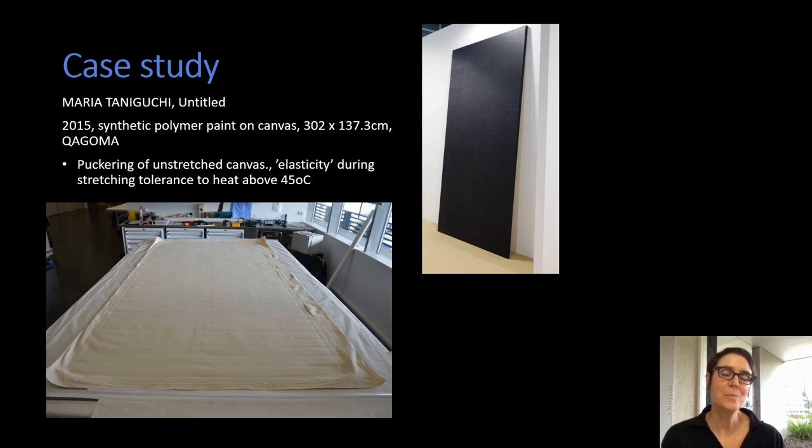Maria Taniguchi, born 1981, is a Philippine artist who is best known for her ongoing series of large brick paintings, which are installed sitting directly on the gallery floor, leaning against the wall. Taniguchi has shown internationally, and this painting was acquired following exhibition in APT8 in 2015. Due to its large size, this painting was transported rolled and was stretched on arrival. The canvas support presented puckering of the unstretched canvas when unrolled. It was also very stretchy and showed tolerance to heat above 45 degrees Celsius.